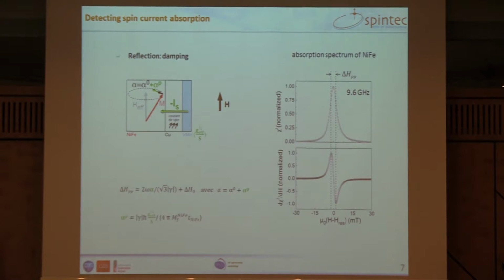This is a typical measurement, so that's the absorption spectrum of our nickel iron, absorption as a function of the field for a fixed frequency. Experimentally, we don't measure this, but we measure this one, which is a derivative because we simply work with a lock-in detection. And we can extract or determine fairly easily the line width of this spectrum.